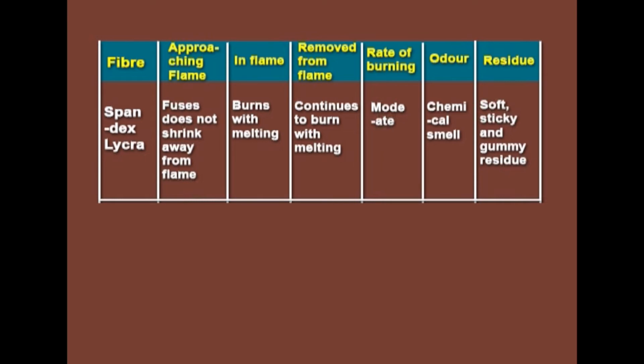When it approaches the flame, it fuses and it does not shrink away from the flame, and in flame it burns with melting, and after removing from the flame it continues to burn with melting, and it gives a chemical smell, and the rate of burning is going to be moderate, and it leaves a soft, sticky and gummy residue because it is a very soft material.